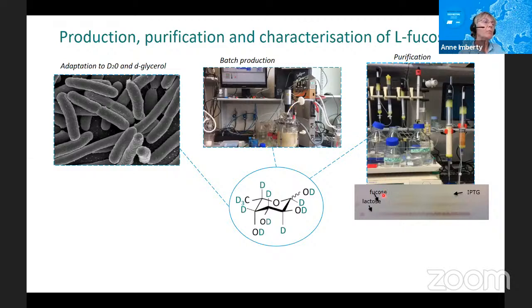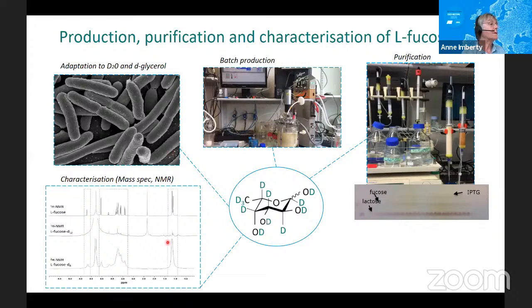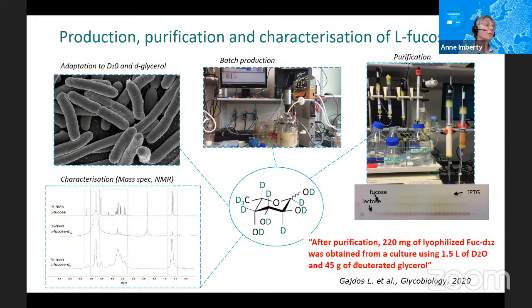Purification is not that simple because you have fucose, which is a small sugar, but it's mixed with other small molecules like lactose or IPTG. So you have to design a precise purification procedure and then characterize the result after purification by mass spectrometry and NMR. And here at the bottom, you have a deuterium spectrum for fucose that can be produced. So at the end, we have the satisfaction to obtain a quite good amount, 220 milligrams of lyophilized perdeuterated fucose, which is sufficient for the study.